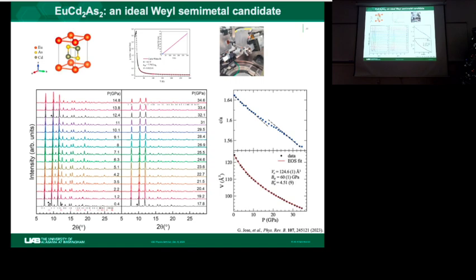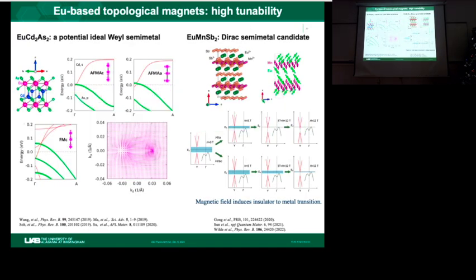in this case. Yes. Can you sort of remind us what is a Weyl semimetal? The Weyl semimetal, okay, so back to this, is because of the spin orbit coupling, and then you have this band inversion near the Fermi level. So in the ideal case, near the Fermi level, you have a linear dispersion, and it shows up as a pair with different chirality. In the ideal Weyl semimetal, these Weyl nodes, Weyl points, appear at the Fermi level.